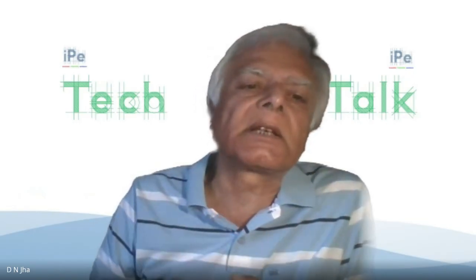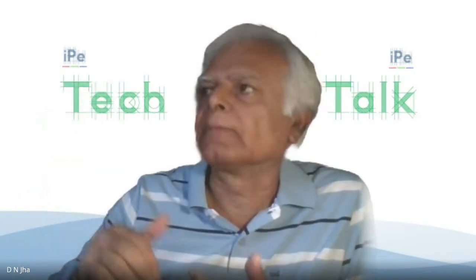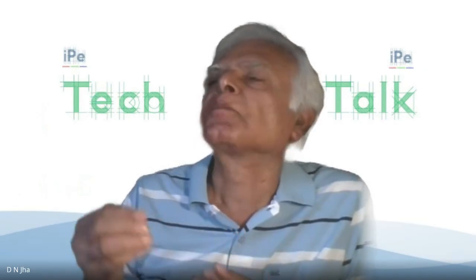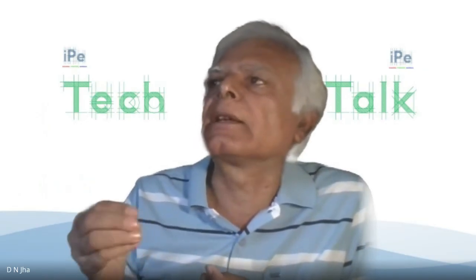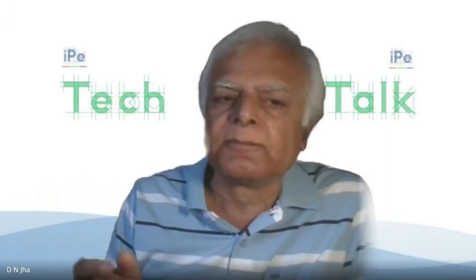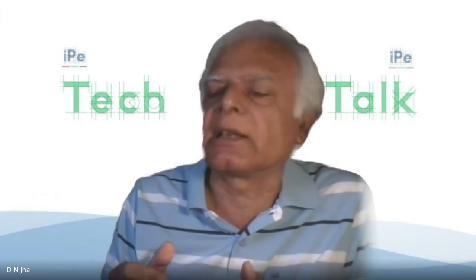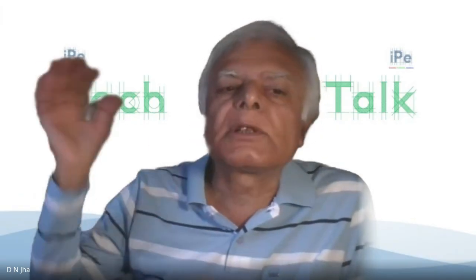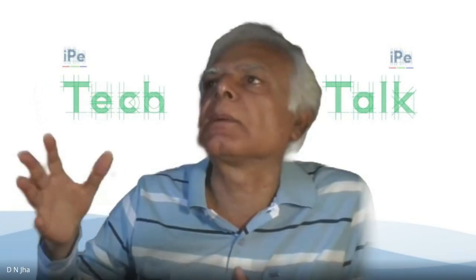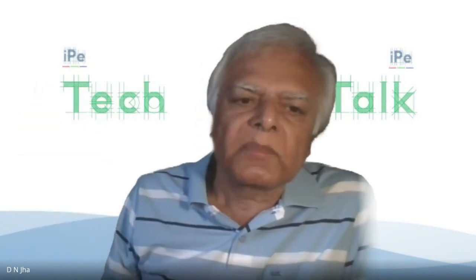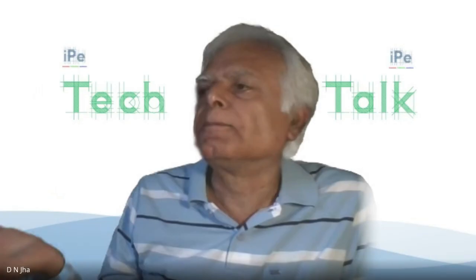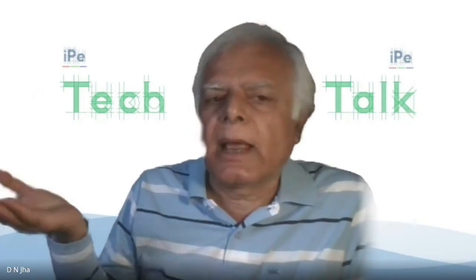Yeah, so you said it rightly, Manojji, that if you have got channeling, in that case, it is having a short circuit kind of, because it is not getting time to interact. The gas is not getting time to interact with the burden very coherently or very consistently. So the CO that is generated at the bottom goes up directly. It bypasses the burden and goes up on the top. And therefore, you have higher top gas temperature. At the same time, the burden is unreduced.